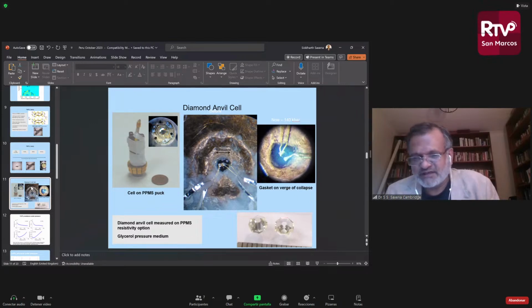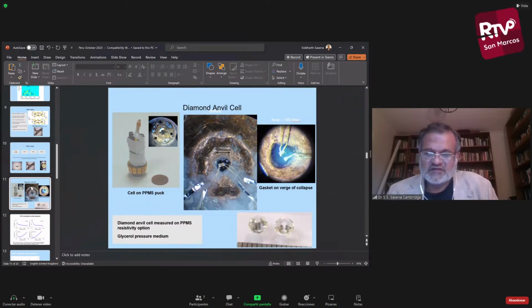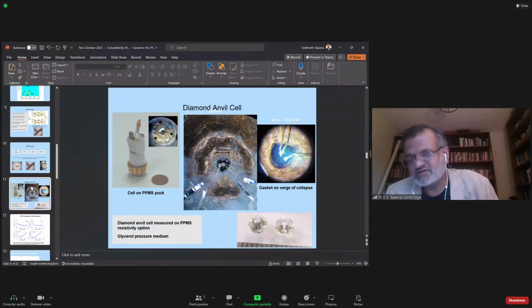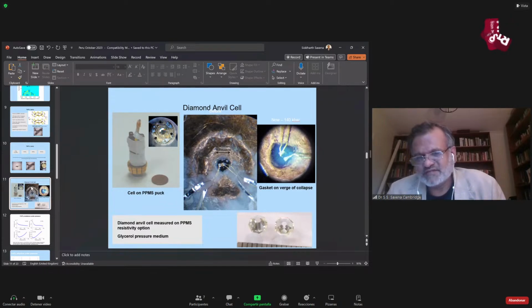And I'll pull back to address the other aspect of your question. We tried to see what this does in a synchrotron data set. We found that although hydrostaticity is not affected, it certainly starts to look more glassy, depending on how you cool the system, and X-ray data starts to become very difficult to do. So for X-ray work, we eventually mostly used either helium or argon as pressure media, which do not cause that problem.